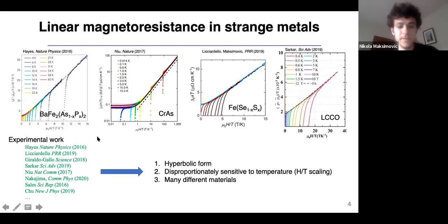The second is that it seems to be kind of disproportionately sensitive to temperature. This was noticed by Ian Hayes originally, where you can just scale magnetic field by temperature and resistivity by temperature, and it seems to capture all of the low temperature data very accurately. And then probably the most beautiful aspect of this data is it seems to apply fairly generically to a bunch of different materials. So I've shown some examples here: chromium arsenide under pressure, iron selenide, the sulfur doped iron selenide, and then electron doped cuprate.